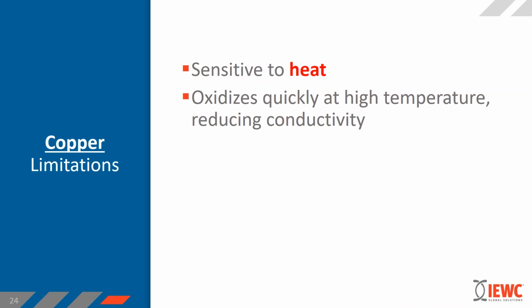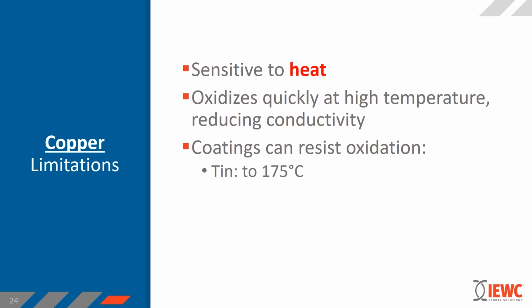So what do we do about it in the wire and cable industry? Well, to resist oxidation, we put plating on the conductor. We'll have a strand that is tin-plated copper. Surely you've seen this. It's called tinned copper. It's called tin-plated copper. And the advantage is that now that same conductor can be used in hotter applications. Tin-plated copper can be used in applications up to 175 degrees. If you need to go even hotter than 175, you'll see silver-plated copper. And even above that, sometimes you'll see nickel-plated copper. So the reason that you have tin-plated copper or silver-plated is all about heat. We're trying to resist the oxidation of the copper. All right?